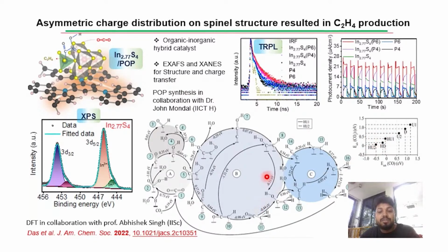From DFT calculation, for the first time, we have proved how CO2 to C2H4 is formed, and almost 10 different energy profile diagrams have been produced, and from there, the best were chosen for CO2 to ethylene production. Here you can see, in this particular case, if the reaction tries to go towards C1 product formation, the energy is very high. Therefore, we are not getting any or very small amounts of C1 products. Rather, it is going towards the C-C coupling reaction, and then finally it is stabilizing this carbon-carbon bound intermediate, which is responsible for the production of non-oxygenated hydrocarbon, which is ethylene over here.